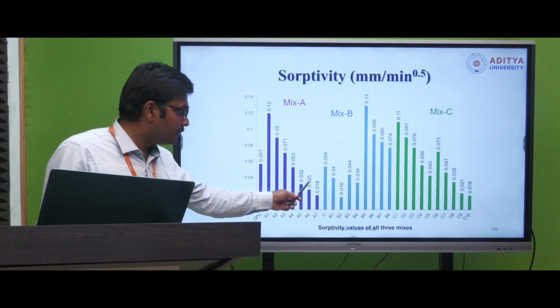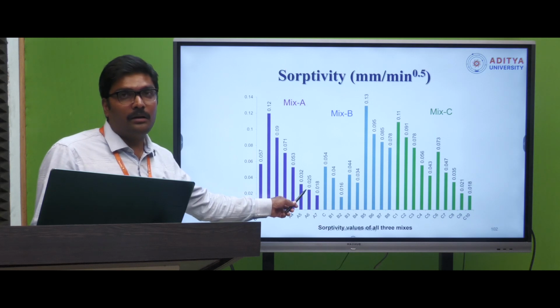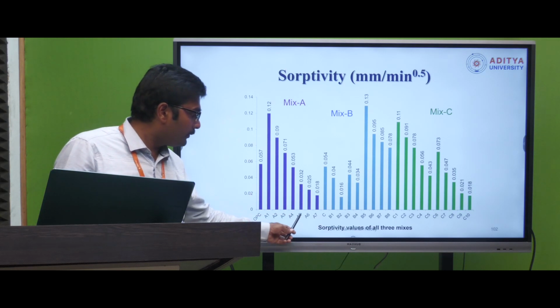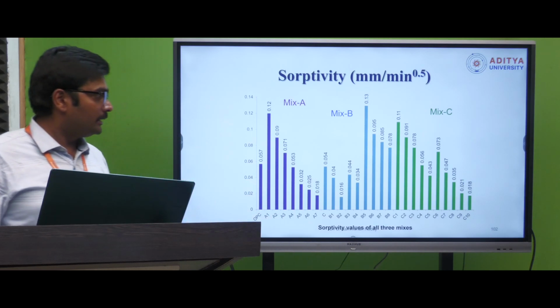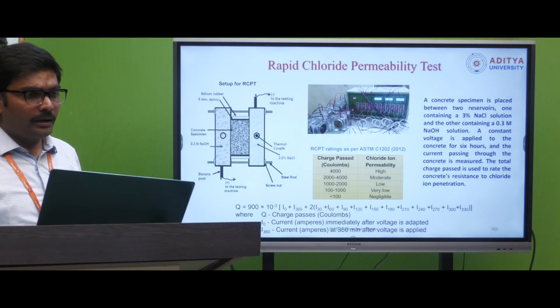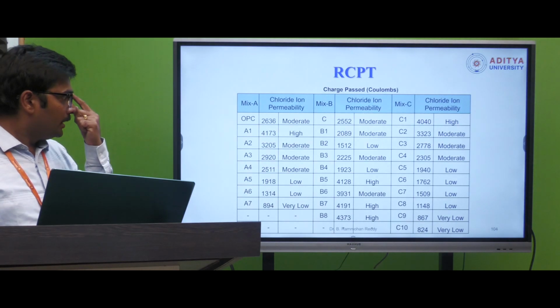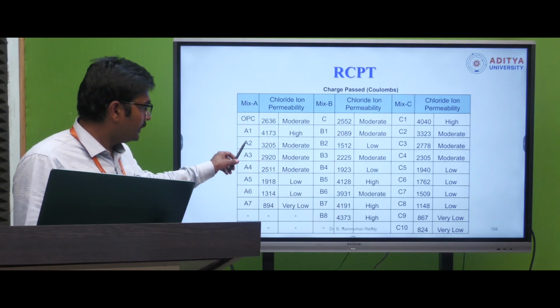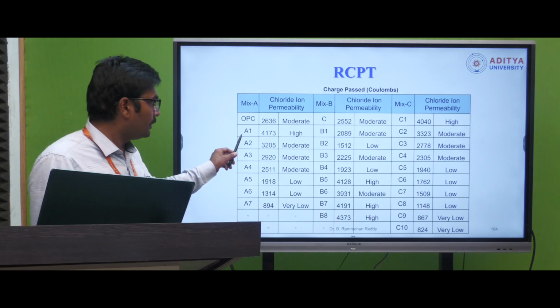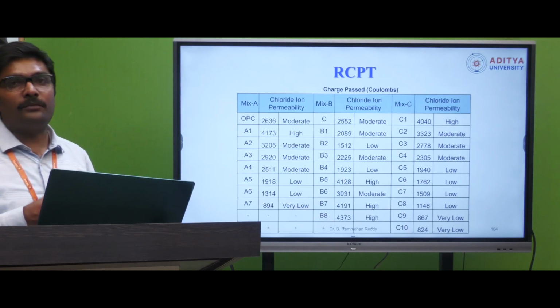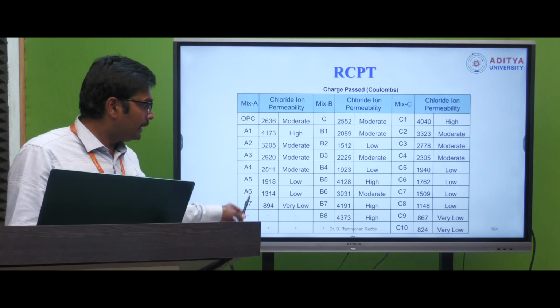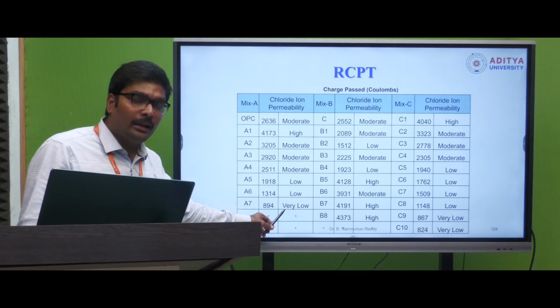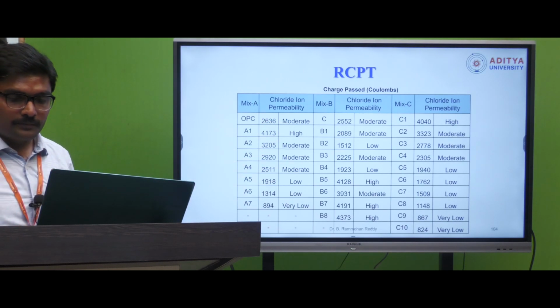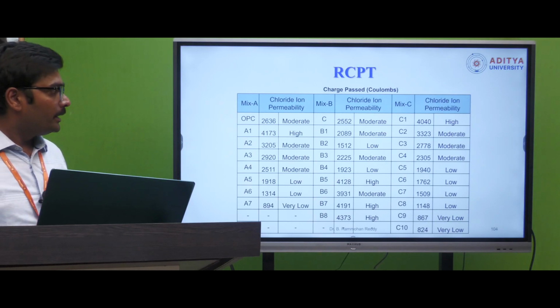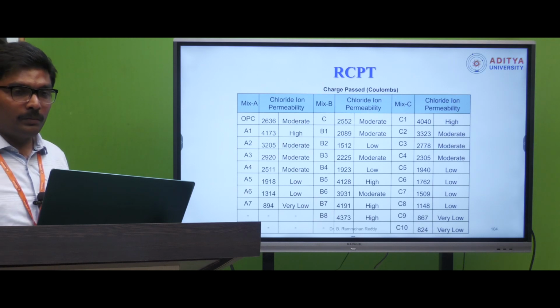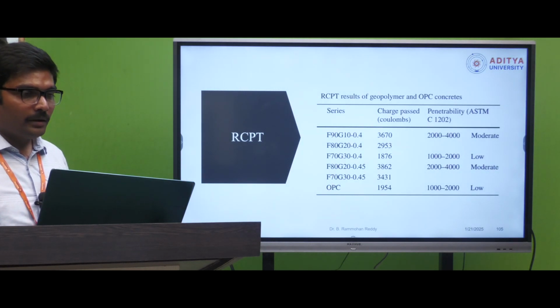The water absorption is reduced once the GGBS quantity is increased in the geopolymer concrete, meaning replacement of fly ash with GGBS gives better, reduced porosity. And another durability property is the rapid chloride penetration test. Here also we can observe the mixes with increasing GGBS content. OPC is the conventional concrete, A1 indicates fly ash based concrete, and A2 indicates replacement of fly ash with GGBS 10%, 20% and so on. With increasing GGBS content we can see the charge passed go from high to very low RCPT values. So it indicates that with increasing GGBS content relative to fly ash, the chloride penetration is less, so we can obtain more durable structures. Another study also presented it in a similar way.